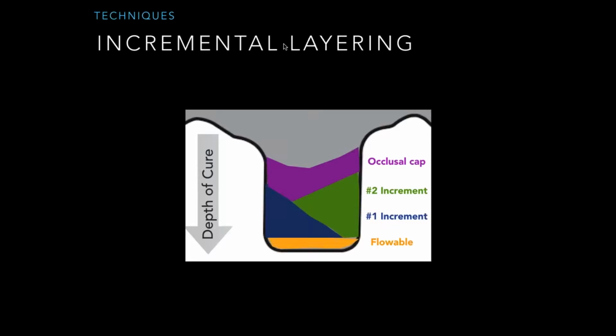So where are we today in the marketplace? And where have we come from, and where are things moving to? Traditionally, composite resins have been placed in increments no greater than 2 millimeters. This 2 millimeter increment allows for adequate photopolymerization of the composite resin that really lessens the polymerization stress that's associated with composites. The thinking here is by reducing the volume of the composite that's polymerized at each placement stage, you maximize the conversion of monomers to